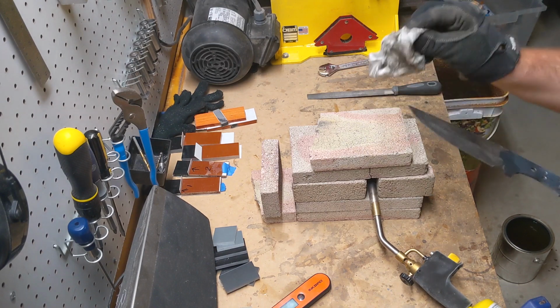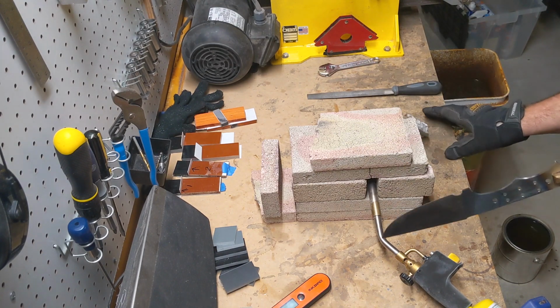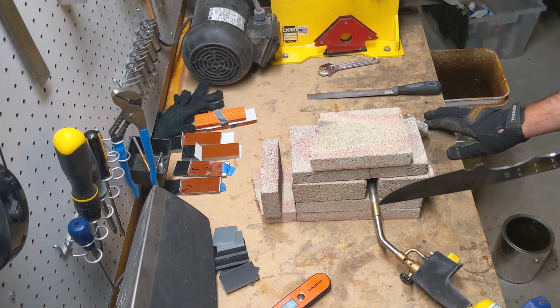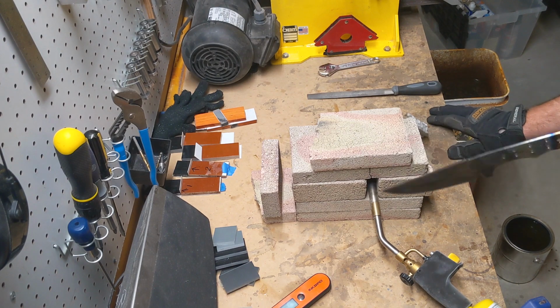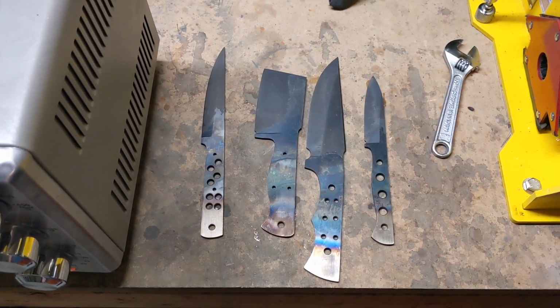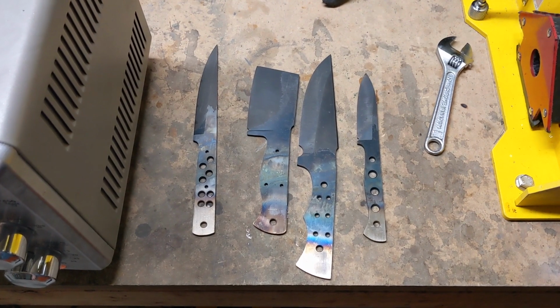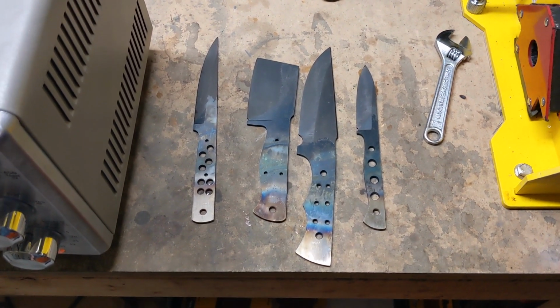I'm going to be doing 2 cycles of 2 hours at 400 degrees. Alright, we've got the knives out of their first tempering cycle of 400 degrees for 2 hours. We're going to stick them back in there for a second one once they're cooled down.